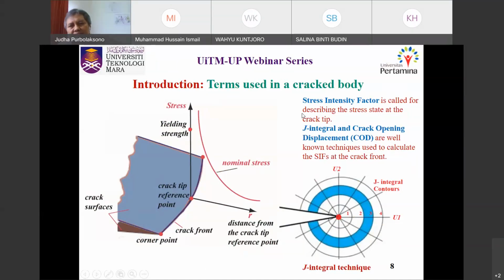So here it's called the stress intensity factor, for describing the stress state in the crack tip or in the crack front here. The most common techniques to calculate or compute the stress intensity factor: the first one is the J integral technique, which I think was proposed around the 1960s. Then also the crack opening displacement. These two techniques are very well known methods used to calculate the stress intensity factor at the crack front or crack tip.